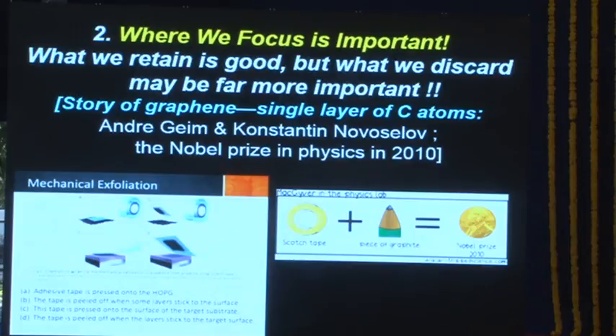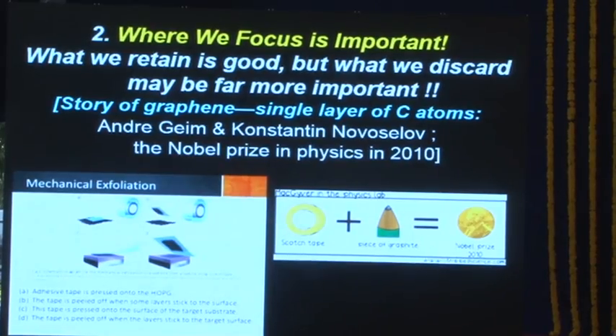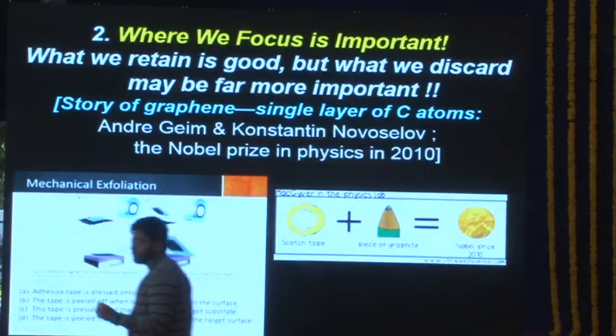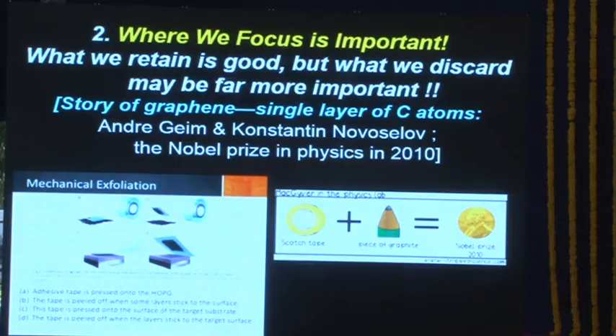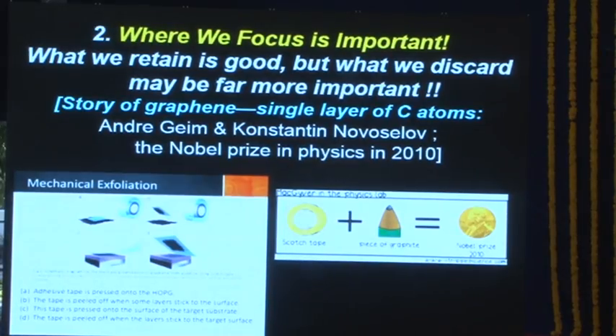So what is so great about this experiment? There's nothing great about this experiment, except that the same experiment was being done for 50 years before graphene was isolated by this method. What people were doing is, if you want to clean the surface of a graphitic block, it's got dirt, it's got debris, so you put the tape and then peel it so that all the debris goes on the tape, and then you have a clean surface of graphite. So what people do, I used to do it myself, is throw away the tape and keep the graphitic block. In this case, the person threw away the graphitic block and kept the tape, right? So it's the same experiment.